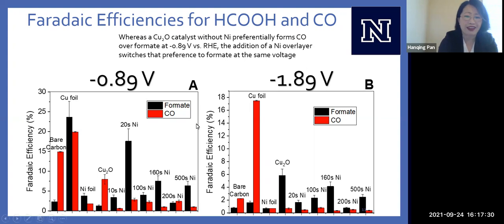There's a lot of data going on here, but the only thing that I want to point out is that if we look at copper oxide without nickel, copper oxide by itself prefers to generate carbon monoxide as compared to formate. But as soon as we put that nickel overlayer, the selectivity changes, it then preferentially makes formate instead of CO. So some kind of synergistic interaction is happening between the copper and the nickel, and it's switching selectivity. There's more to dig into there.